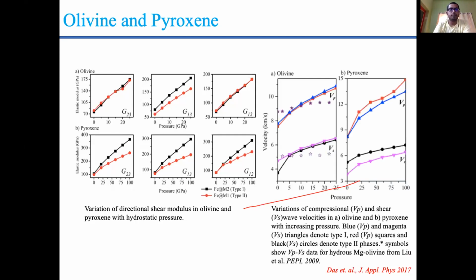In case of olivine, you can see the shear wave velocity decreases at ambient condition, but with pressure, it becomes nearly the same. And it also agrees with the experimental value by Liu et al. This star mark is the values for Liu et al. Whereas in case of pyroxene, you can see there is a jump in the shear wave velocity even at ambient pressure, which stays almost equal at high pressure. So this jump in pyroxene corresponds to the Hales discontinuity.